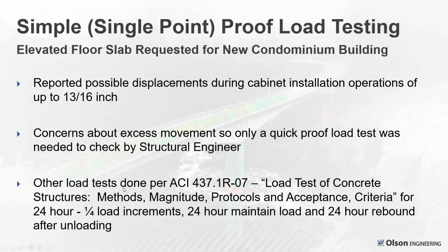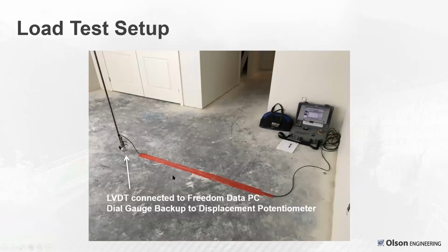If you're doing a full-blown load test of a floor area, it can be done per ACI 437, which talks about the load test of concrete structures. Basically, in this case, per the code, you would do 24 hours where you would increase the load by quarter load increments, maintain that load for 24 hours, and then a 24-hour rebound after unloading in which it has to recover to, if memory serves me, about 70% or better of where it started from. So that's a more full-blown load test. But in this case, it was a straightforward, how stiff is it load test to just make sure it wasn't too flexible. So this shows the equipment we used.